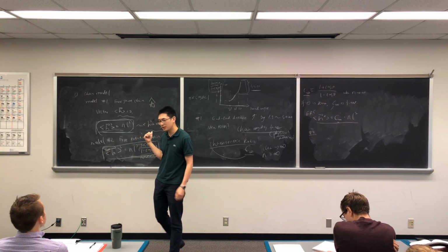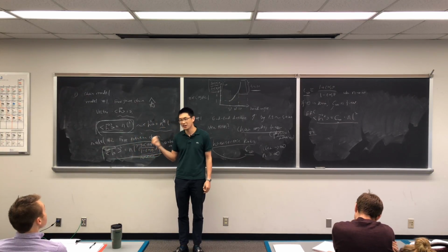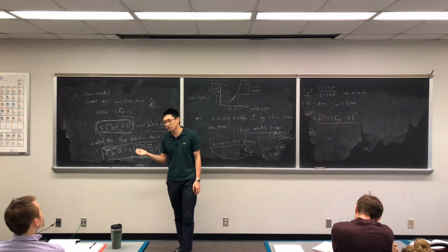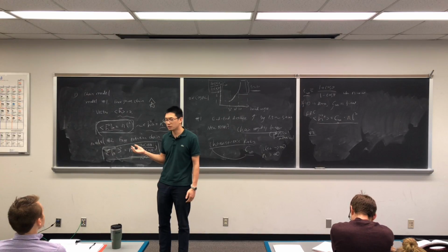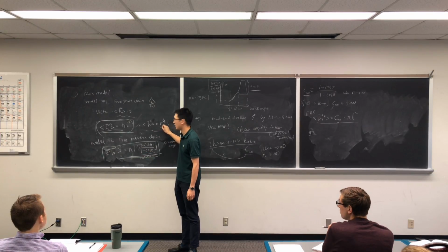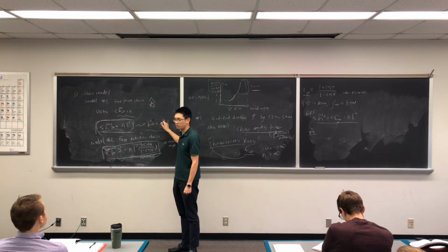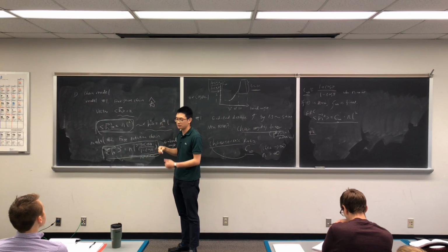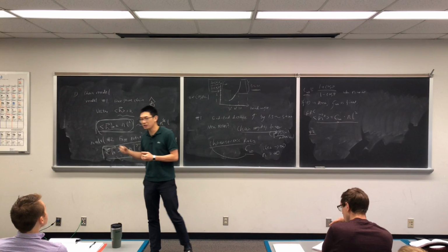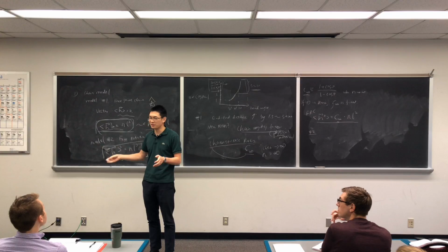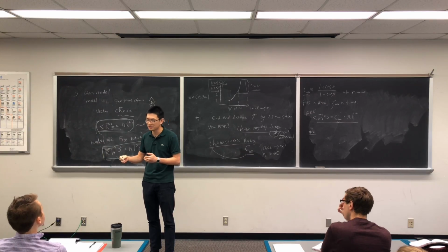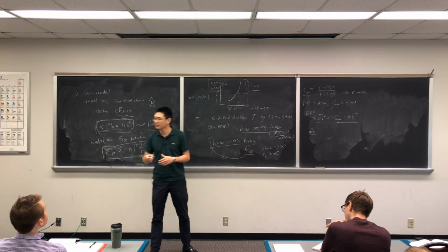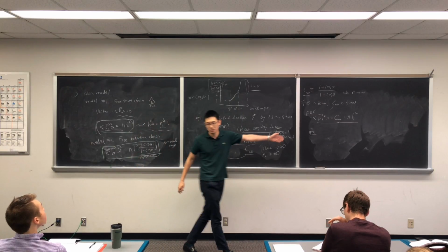In the free joint chain, end-to-end distance h equals N to the half times L. Or, this is proportional to n root square, right? So you need to increase the bonds 100 times, then end-to-end distance increases 10 times. Okay? The same works for the free rotation chain.